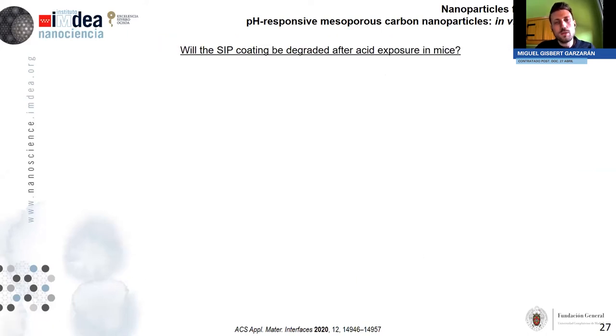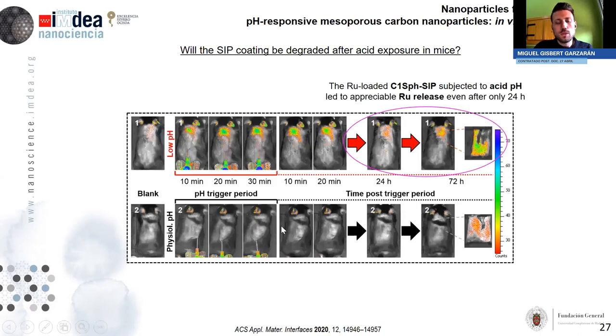So after that, we know the nanoparticles are biocompatible. We know that they remain effective in physiological conditions, but what happens if we have an acid scenario? For that, we did this experiment. We have two groups. In this one, we have animals that received the nanoparticles at physiological pH. And here we had some animals that received the nanoparticles in an acid solution. They got three injections of acid solution for 30 minutes. We observed that just 30 minutes of exposure to acid pH was more than enough to trigger the drug release. It is clear that in the case of physiological pH, the dye remained confined within the pores, within the nanoparticles.